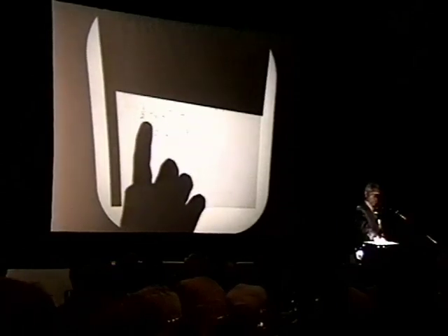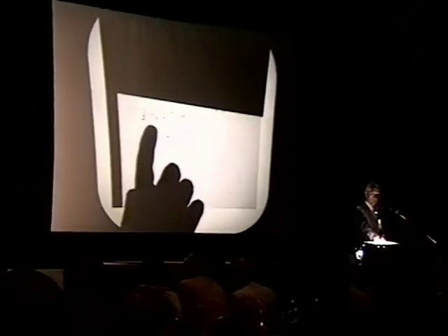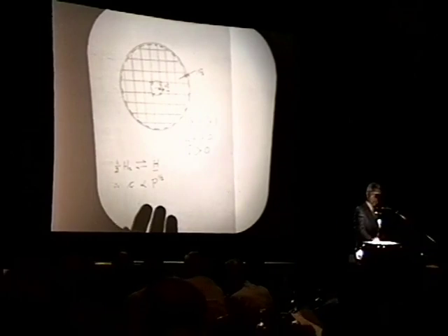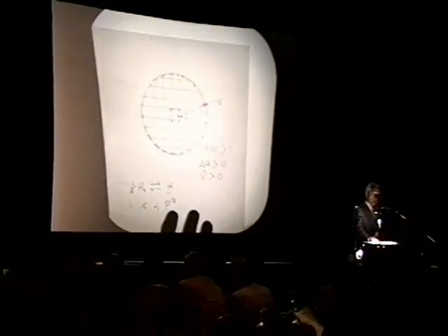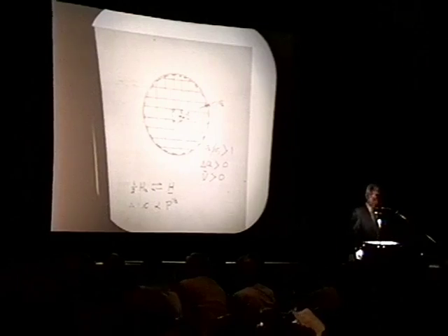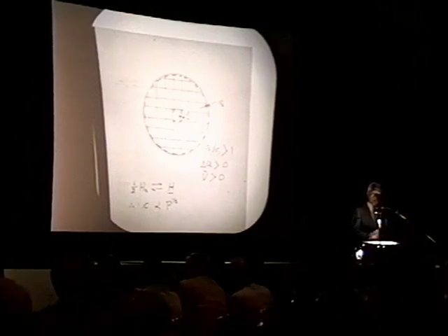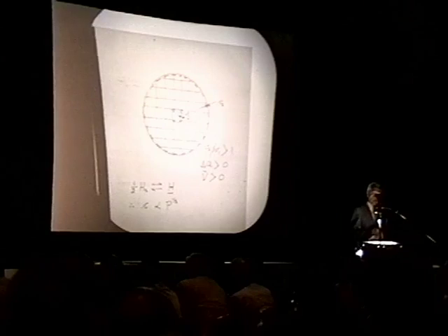That's consistent with this kind of chemical equilibrium, where the molecule dissociates. So from this we know that, at least at very low concentrations, the hydrogen and deuterium in the solid is in fact dissociated. It occupies the interstitial position. We know that because the partial molar volume is a positive quantity, the lattice parameter increases. I'd like to show you how to visualize what happens in the lattice, following a simple model that simulates, from the elasticity point of view, what happens.